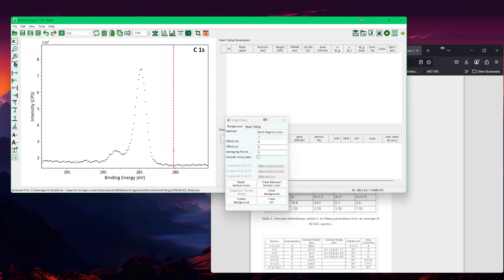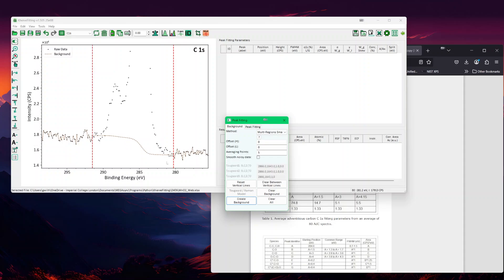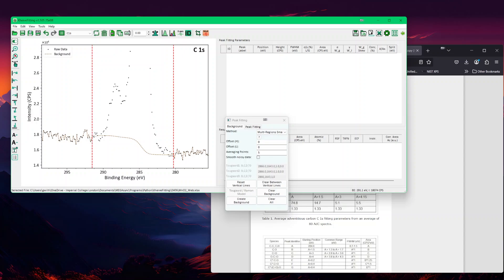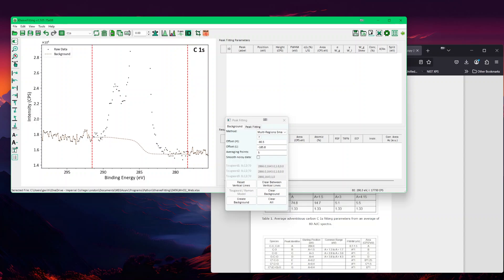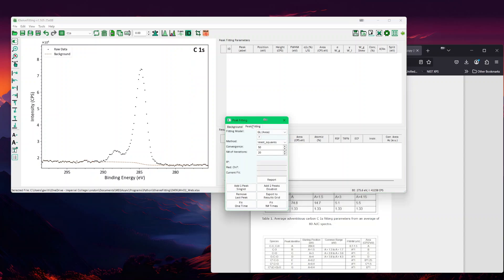At first, you would do a range using the vertical line here. You just click on the plot and you choose a range around there. Then you simply create a background. You can see that because the background is going up, it's created a Shirley background. If you click on control down, you can actually zoom in into the noise. From there, you can also play with the offset using the shift key. If you press the shift key, usually it's not going to work the first time, so you un-press it and then re-press it, then you can play with the background. This is now good enough, I can zoom out using this right click zoom out. Now I'm getting to something quite nice.